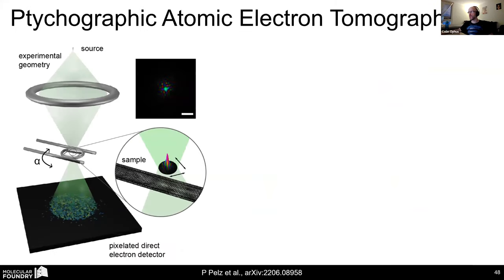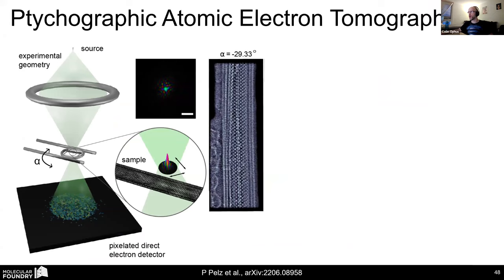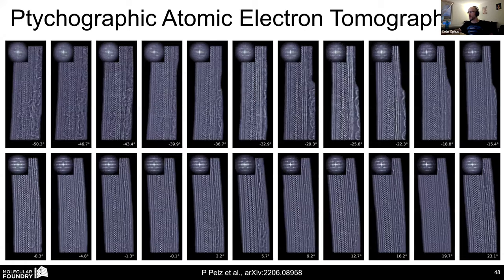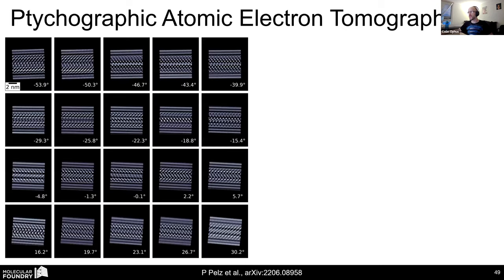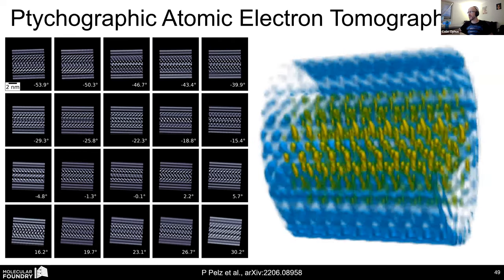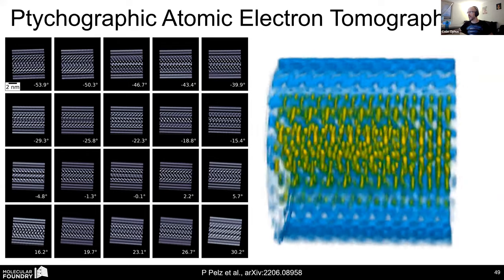Here's an example that we just published that's sitting on the arXiv, currently under review, of a carbon double wall nanotube with a zirconium telluride nanowire encapsulated inside the tube. Here are tilt series, and you really have to do the ptychography to get dose efficient imaging at all these different angles. If you used the incoherent imaging, you would absolutely destroy the material here. After we did that, in order to boost the signal to noise, we did some class averaging, taking a page out of biological studies, and then reconstructed it in 3D, this class average structure here.